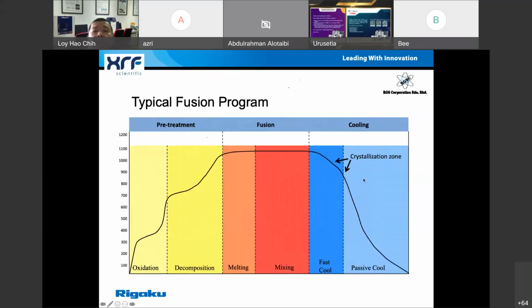This is a typical fusion process, looking like a temperature curve. Normally the flux will start to decompose somewhere around 700 to 800 degrees, or maybe 900, depending on the flux. When the lithium flux decomposes and starts to melt, it melts together with your samples. And we agitate the platinum crucible inside the furnace to ensure that everything is mixed well. When it's mixed well, we pour it out into a casting dish or mold.